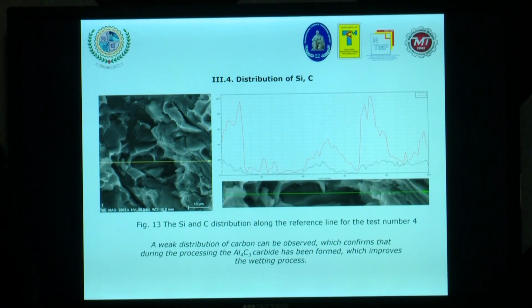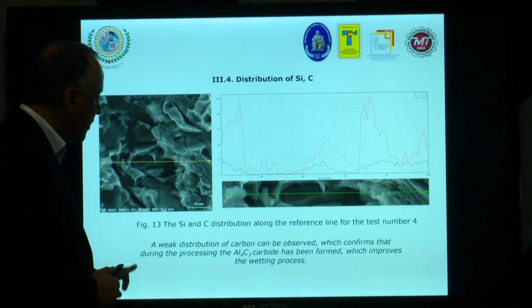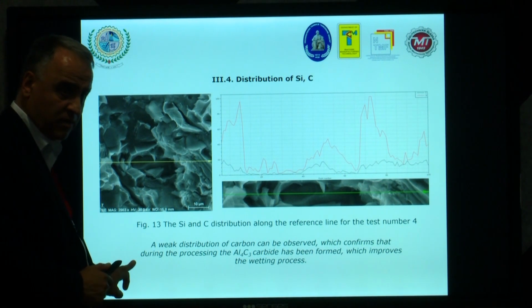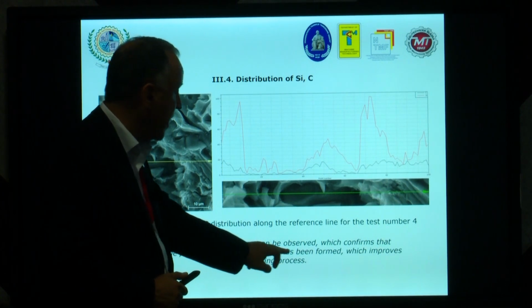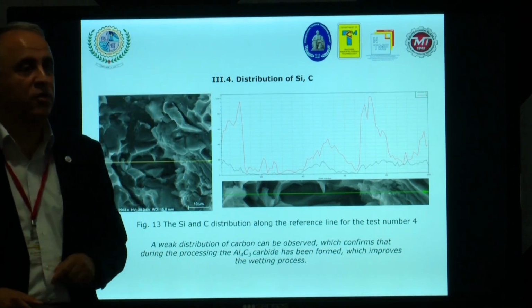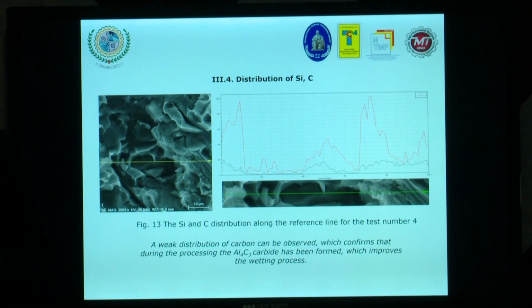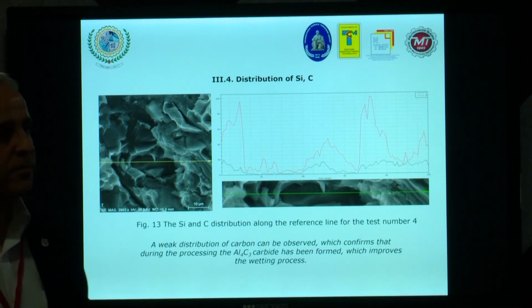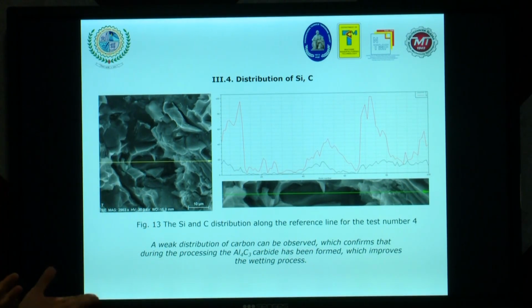So the weak distribution of the carbon can be observed, which confirms what? That during the processing, aluminum carbide has been formed. This is quite important because it improves the wetting process. Wettability. This is, let's say, the main conclusion from this point of view.